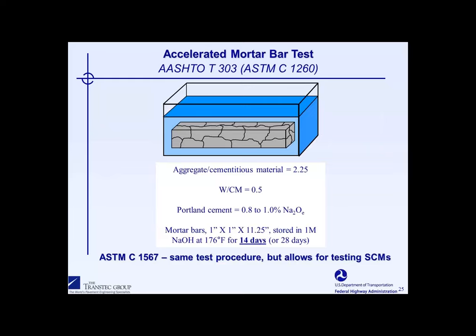So let's switch gears now and talk about the accelerated mortar bar test. The accelerated mortar bar test was originally developed in South Africa. This is a test that tests small mortar bars, 1-inch by 1-inch cross-section. But you'll notice a fundamental difference between this test and all the other tests, and that is the bars are actually stored in a sodium hydroxide solution. It's a 1-normal sodium hydroxide solution, and the temperature for testing is 80 degrees Celsius.